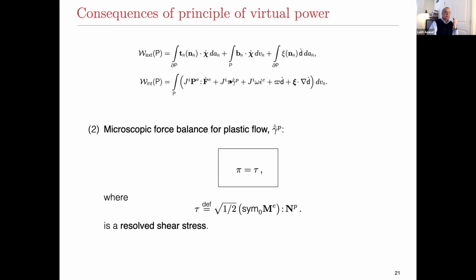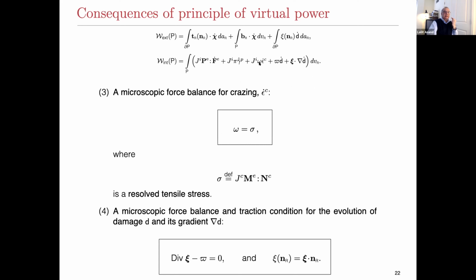So that was the first balance. Then we have this force pi, which is conjugate to gamma bar dot P. That scalar microforce is balanced by a stress tau, which is the symmetric deviatoric part of the Mandel stress dotted with the direction of plastic flow. So that's the resolved shear stress. So pi is balanced by a resolved shear stress. Similarly, this omega, which is conjugate to epsilon dot C, the craze strain rate, is balanced by a resolved tensile stress, which is the Mandel stress dotted with the direction of crazing.